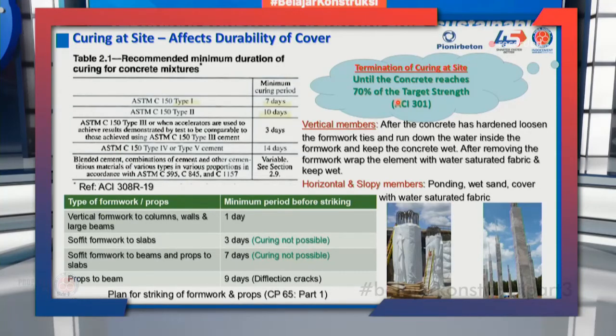There's also a guideline based on ACI. If you use ASTM C150, that is your OPC Type 1, you have to do minimum 7 days wet curing. If you use ASTM Type 2, which is slow, it takes 10 days. If you use ASTM Type 5, which people normally use in Indonesia for sulfate resistance, it takes more, 14 days it requires. But if you use blended cement, you have to verify how many days it takes to achieve 70% of the target strength. It depends upon your composition of the SCMs. Normally it is 14 days. I take 14 days.